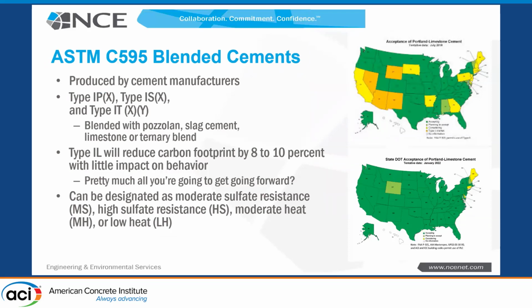As I said, the real push is in this idea of using the blended cements, the 595s. They can be a IP, which is blended with pozzolan, a IS blended with slag cement, a 1L, which is blended with limestone, or a IT, which is blended with two of those. It could be a limestone with a pozzolan, limestone with a slag, two pozzolans of that type. Typically just the 1L, depending on who you talk to, might reduce your carbon footprint 7 to 9%, 8 to 10%. So it's an immediate reduction. And it's designed to be fairly seamless.